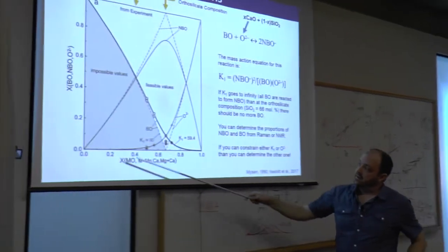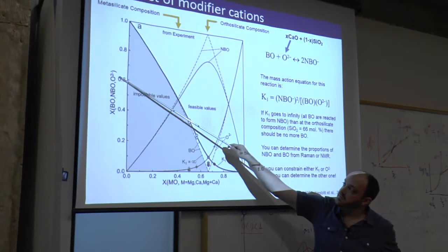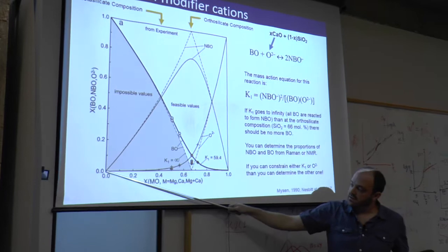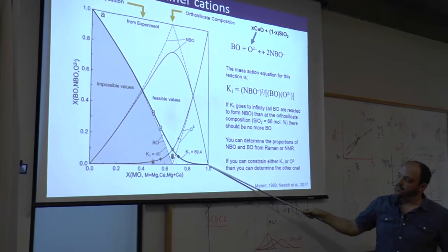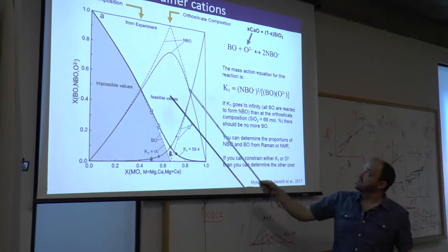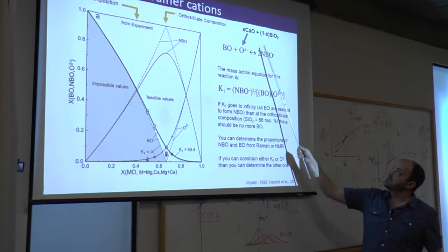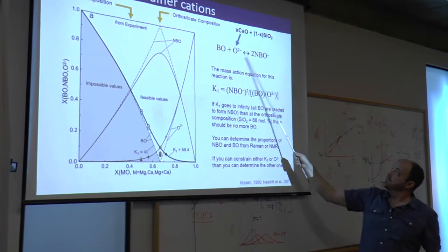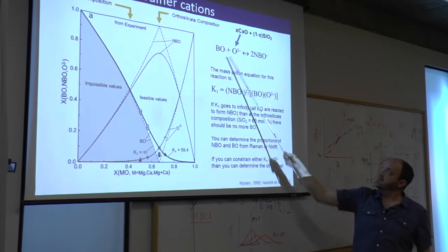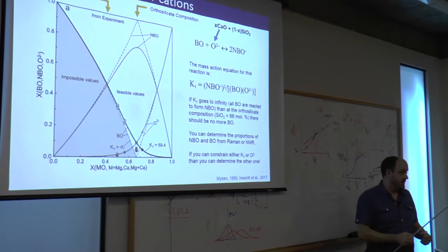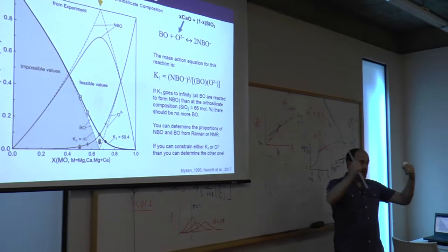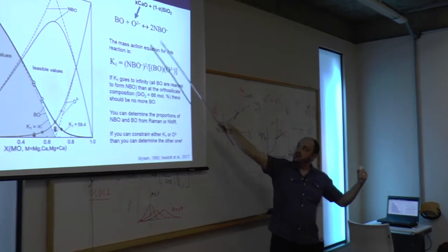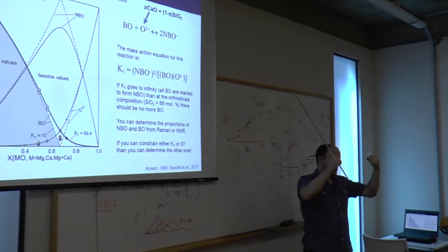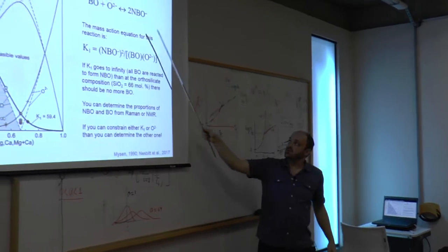So if we look at the different proportions of the oxygen species, as you take pure silica and add a modifier, you have to produce continually more non-bridging oxygens, to the tune of 2 non-bridging oxygens for every bridging oxygen you break. You have 1 bridging oxygen, you break that bond, and you need the extra oxygen to join the tetrahedra that's lost an oxygen. So you produce 2 non-bridging oxygens.